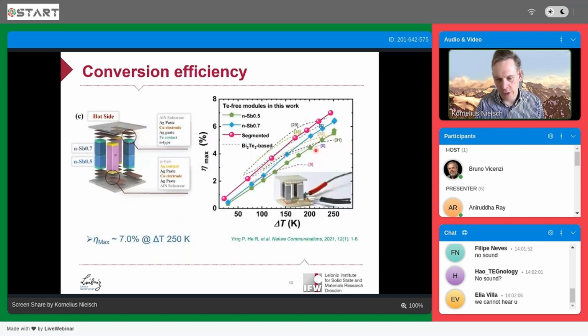When we built the first thermoelectric modules roughly four years ago, you could see that with the lower antimony composition we had an efficiency of up to about 5%, when applying a temperature gradient of 250 degrees. When we switched to the higher antimony composition N-type material, we achieved about 6%. And when we combined this segmented design, we achieved directly about 7% in the first attempt. This is already very competitive with bismuth telluride.